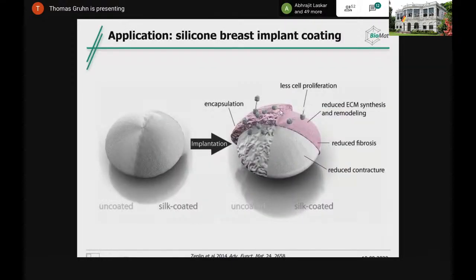Well, it's good for coatings of implants, and this is a quite old story where we actually coated a silicone breast implant with spider silk, and here just half of it is coated to show you the effect that we really selectively can bind cells on the surface. We avoid an immune response, and therefore we also avoid the formation of a capsule. And this capsule can also inflame and can cause what is called a capsular fibrosis. And we could show that coating of silicone implants with spider silk prevents capsule formation.